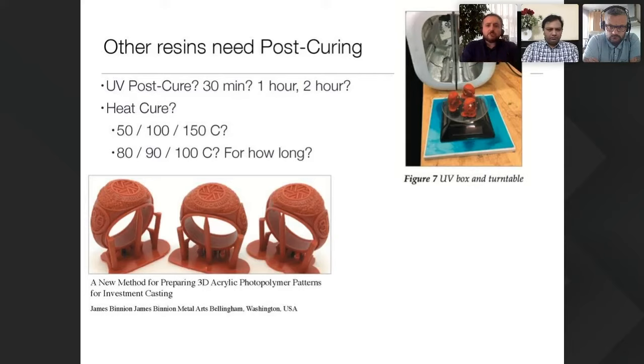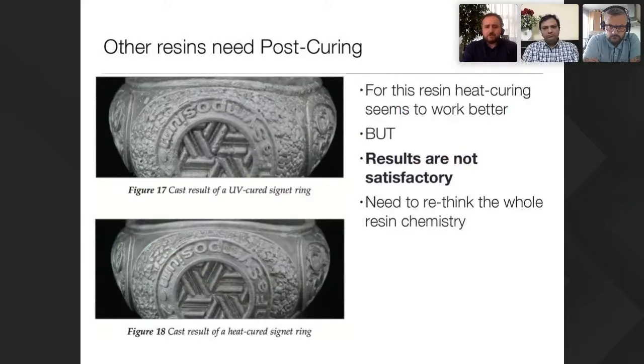I repeat, you don't need to do this for our resin - this is just a paper made for other resins. Let's see the results. For that particular resin, if they UV cured, you have the casting result on top, and if you heat cure, you have the casting on the bottom. There is a slight improvement, but according to me, and I guess to everybody, this is not really satisfactory.